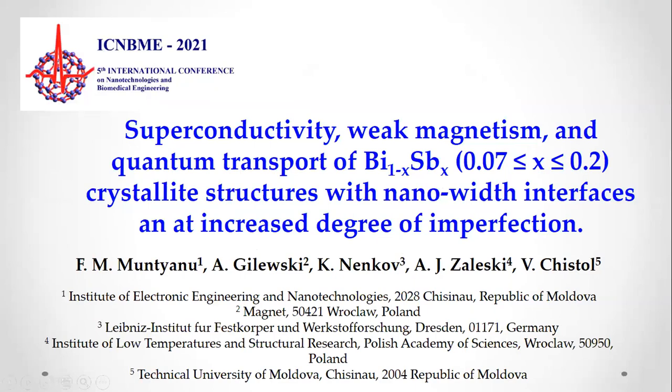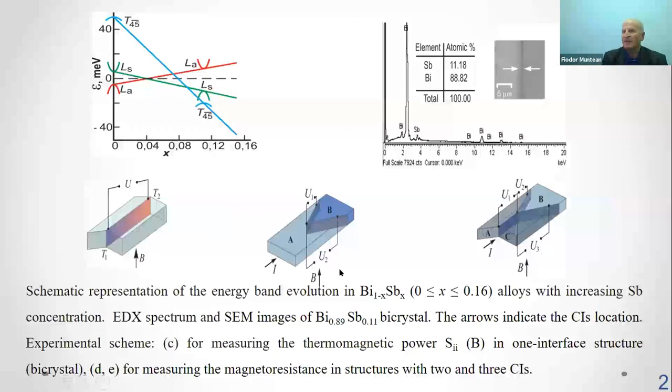Sampling for measurement consists of bulk singly crystalline disoriented blocks crystallite and one or more nano-width interfaces with a pronounced degree of imperfections. The interfaces was of a solitary central layer about 60 nanometers and two similar adjacent about 20 nanometer layers.